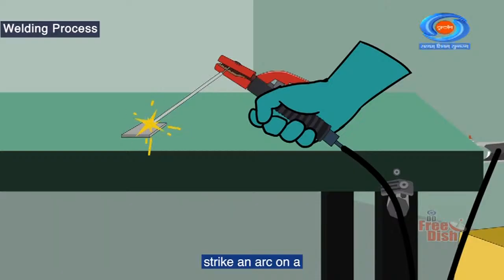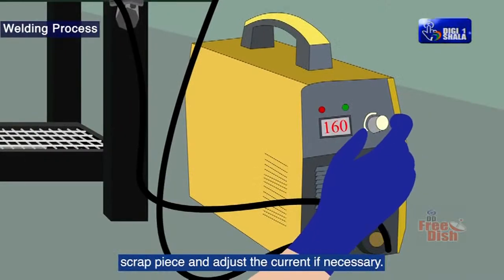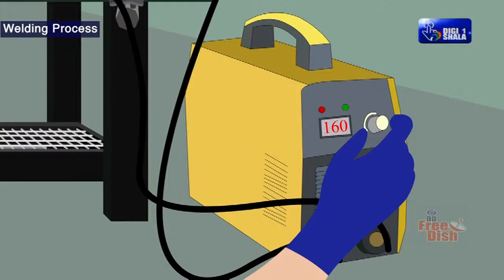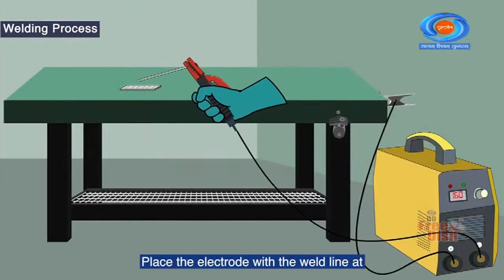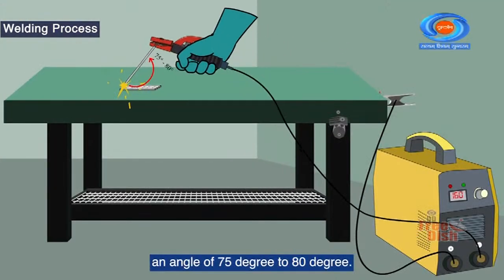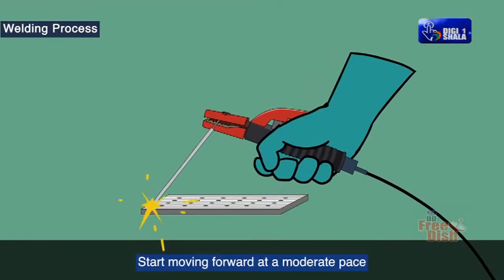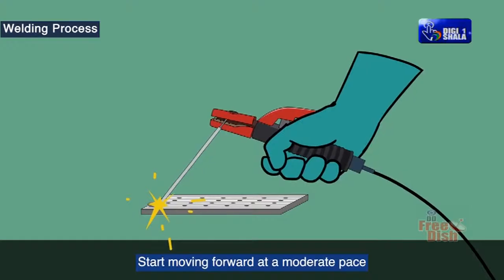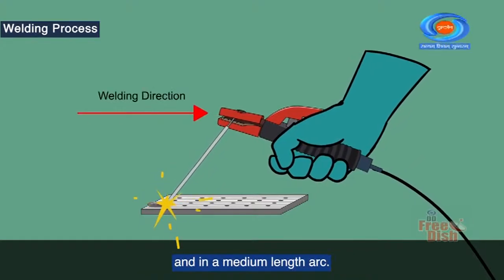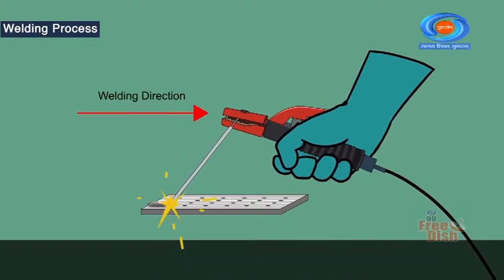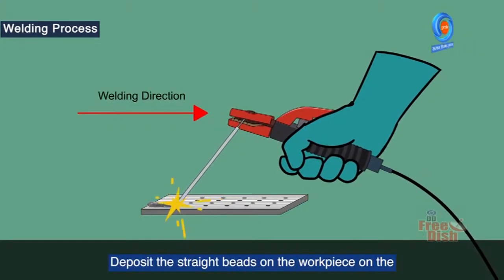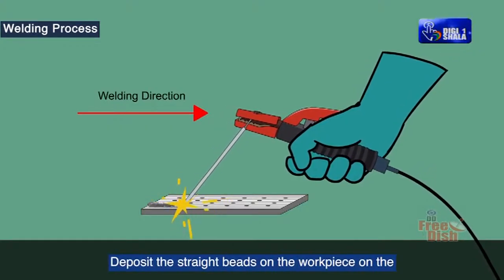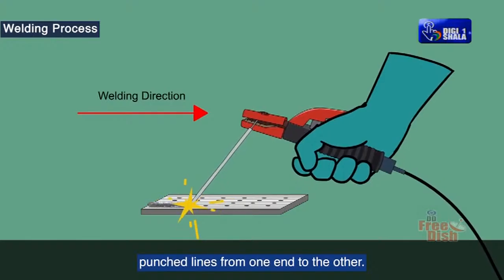Strike an arc on a scrap piece and adjust the current if necessary. Place the electrode with the weld line at an angle of 75 degree to 80 degree. Start moving forward at a moderate pace and in a medium length arc. Deposit the straight beads on the workpiece on the punched lines from one end to the other.